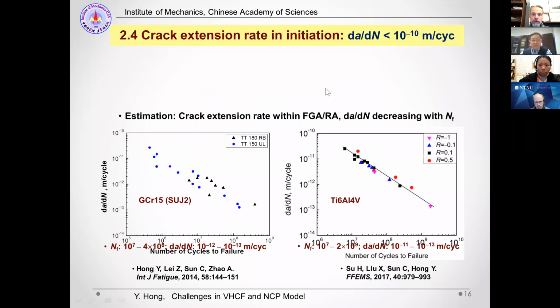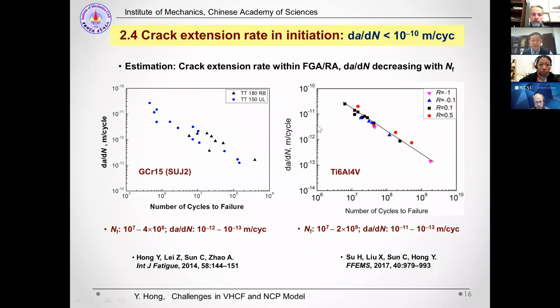And then the fourth point is about crack extension rate in initiation. We have been talking about the initiation life, and also we know the size of this initiation zone, and then we can obtain an average value for the crack initiation extension rate. I like to use the term extension instead of growth. The extension rate for high strength steel is between 10 to the minus 12 and 10 to the minus 13 meter per cycle, and for titanium alloy between 10 to the minus 11 and 10 to the minus 13 meter per cycle.